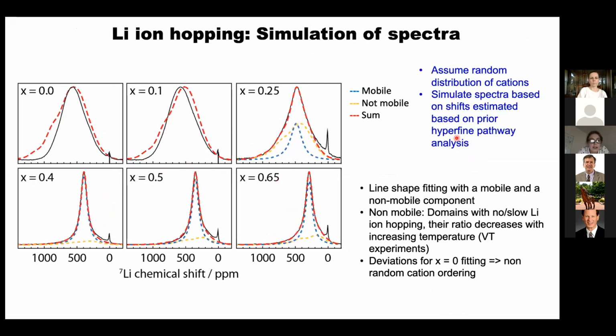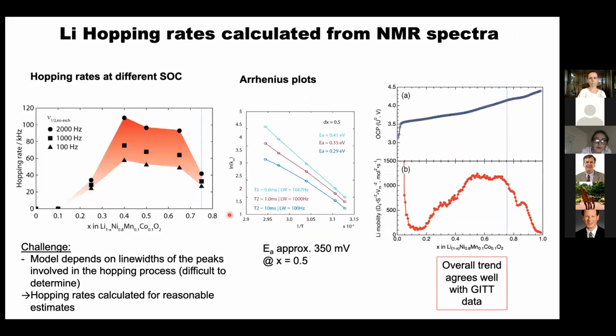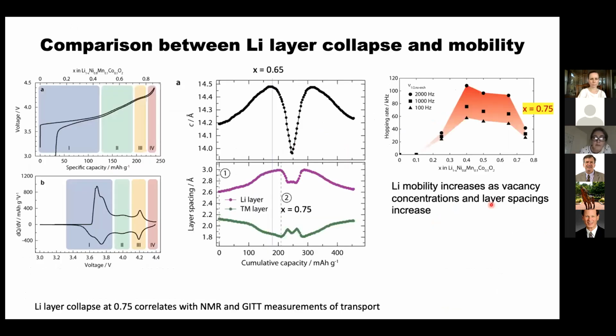And so my postdoc Katerina did a nice study where she modeled the whole thing and was able to fit the spectrum. And by doing that, she was able to quantify the hopping frequency as a function of state of charge. And basically beyond about 0.25, the lithium starts to move, but at 0.75, they stop moving. And then you can do similar electrochemistry experiments, or not similar ones, to confirm that. And so if you go back to this model we had of the structure, you can correlate this drop in the lithium transport at 0.75 with where the lithium layer collapses. And so you can then see that that will pull them together, and that will result in reduced lithium capacity.